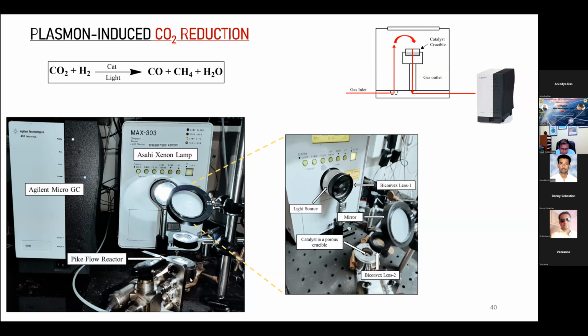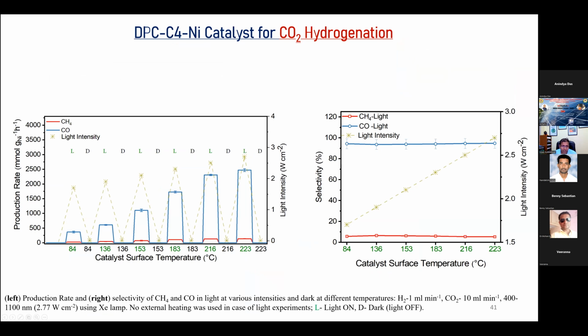These are the results. First we carried out the blank dark reaction, no light, with DPC-C4-Ni. You can see at 84, 136, up to 223 degrees Celsius we observed no activity. However, as soon as we switch on the light at different intensities, say 2 watts per centimeter squared, between 2 to 3 watts per centimeter squared...